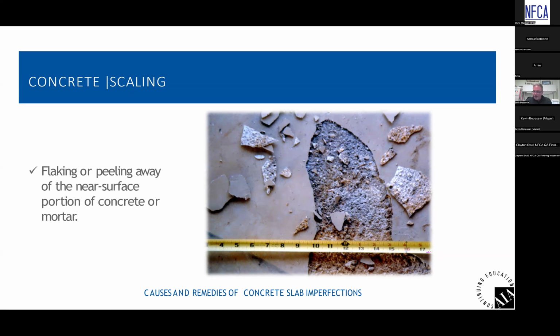They entrain air, maybe 8%, 10% air for exterior applications, so that you have all these voids in cured concrete for water to go and freeze and expand and not affect the concrete. Unfortunately, it sometimes gets used inside and gets steel troweled, and it should never be steel troweled.